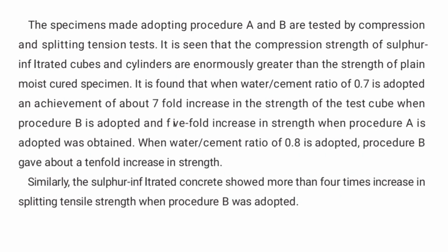The specimens made adopting procedures A and B are tested by compression and splitting tension tests. It is seen that the compression strength of sulphur infiltrated cubes and cylinders is enormously greater than the strength of plain moist cured specimens.